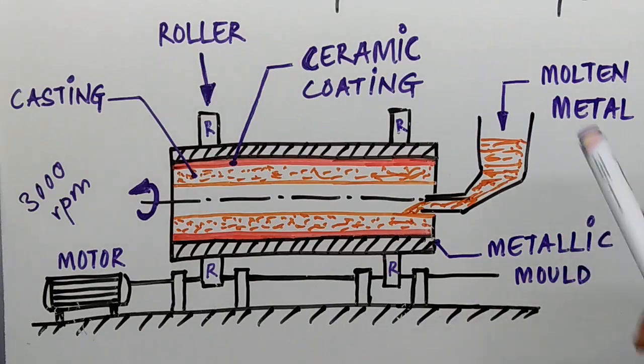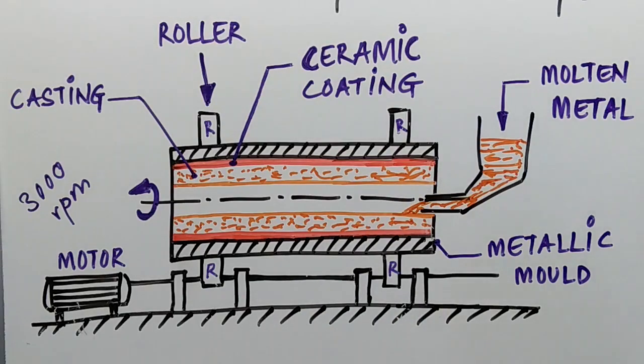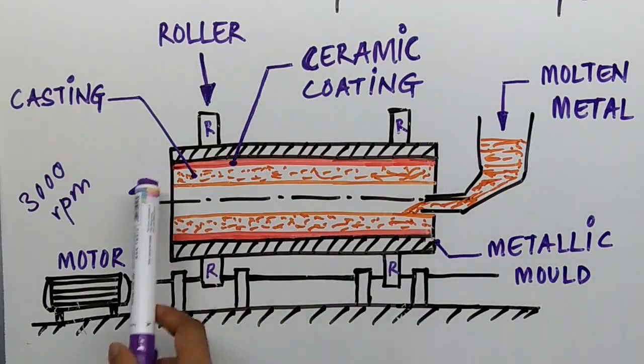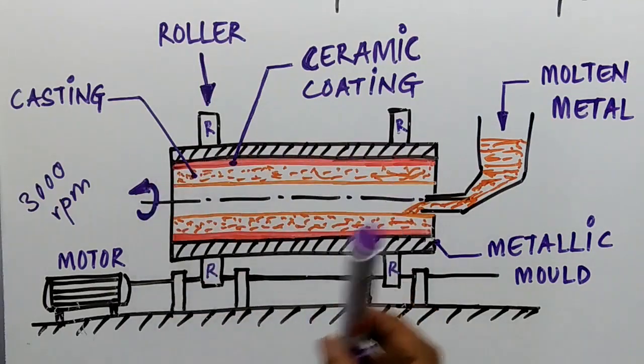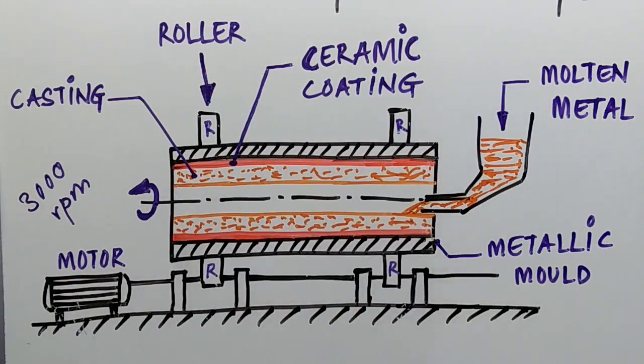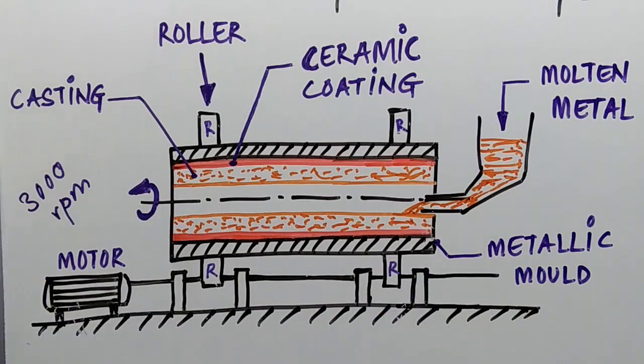While the mold is rotating, molten metal is poured into the pouring basin. As soon as it enters the mold, it is subjected to centrifugal force. Depending on the density, the alloying components are deposited towards the wall or towards the center — high-density components go towards the wall, lower-density ones towards the center. Lighter impurities also settle towards the center and are removed during finishing.